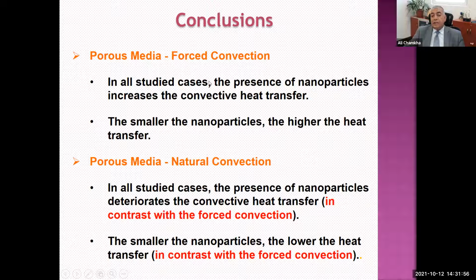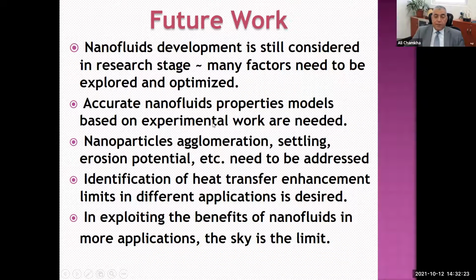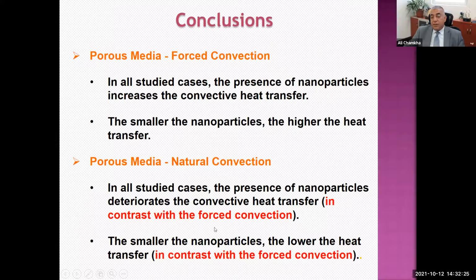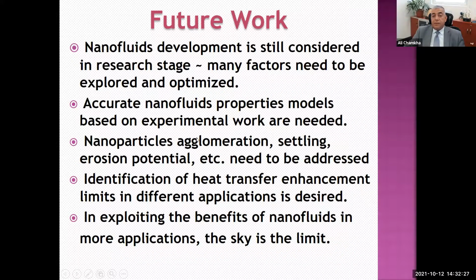Porous media, natural convection, that's forced, horizontal plate. This is vertical plate, natural convection. In all studied cases, the presence of nanoparticles deteriorates the convective heat transfer. This is in total contrast with the forced convection here. The smaller the nanoparticles, the lower the heat transfer. This is in contrast with the forced convection as well. So whether you have forced or natural convection, you have different results for these cases.